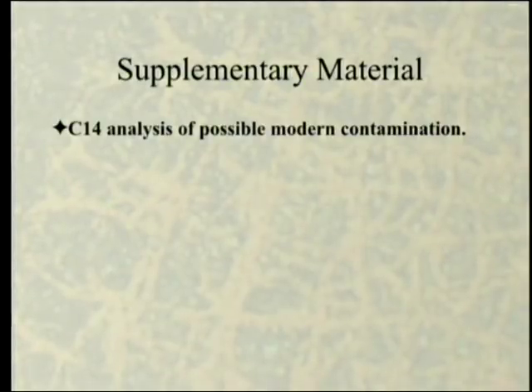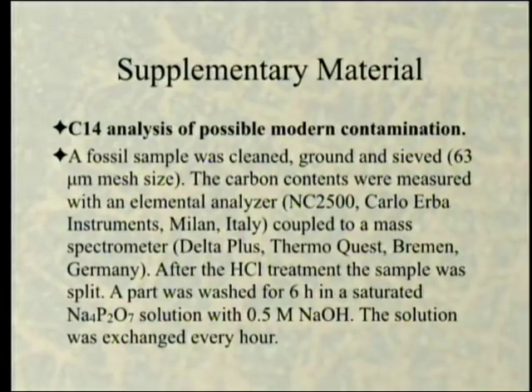Maybe they still can't be, and they're just overestimating the age. But anyway, carbon-14 analysis of possible modern contamination. This is the part that got me really interested. Fossil sample was cleaned, ground, and sieved, 63 micron mesh size. Carbon contents were measured with an elemental analyzer, so they took this stuff, ground it up, put it in, and they measured how much carbon was there to make sure that they actually had enough carbon to do the job, and coupled with a mass spectrometer, so they fed this into this fancy machine.